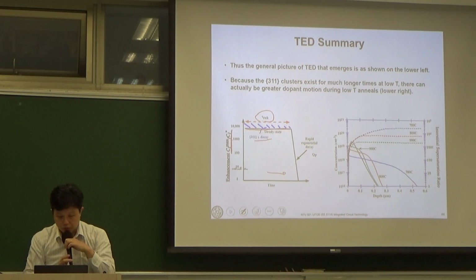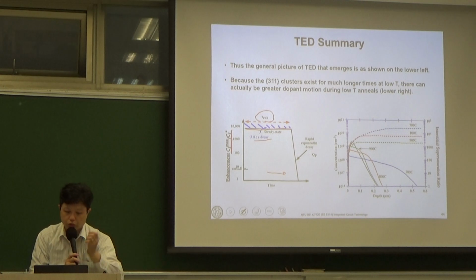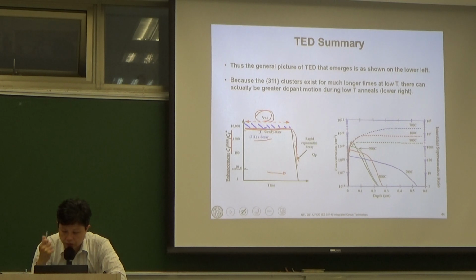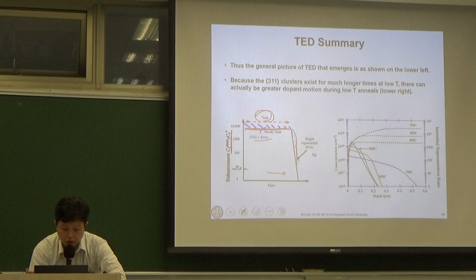These blue lines become shorter and shorter, which means the cluster begins to decay. During this time of enhancement, we see that this CI max still remains at a very high level, and then it quickly drops exponentially.